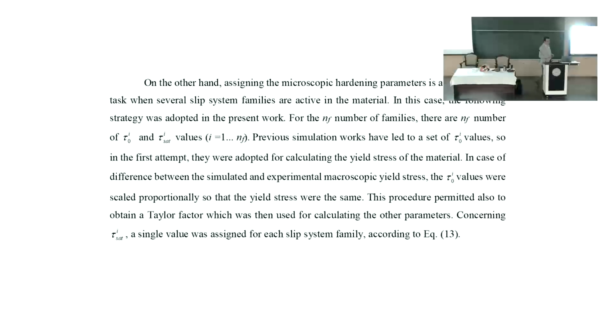Okay, so finally, what happens is a simple process. By going from these empirical parameters to crystal plasticity initial simulation values, we can try how the polycrystal model reproduces the macroscopic stress-strain curve. If you see any deviation, you might still have to fine-tune the polycrystal model parameters.